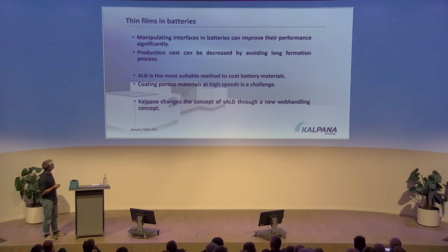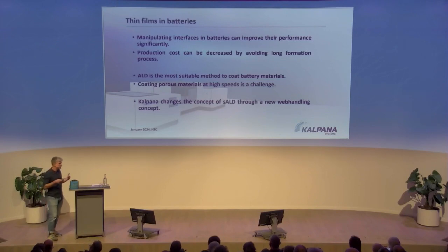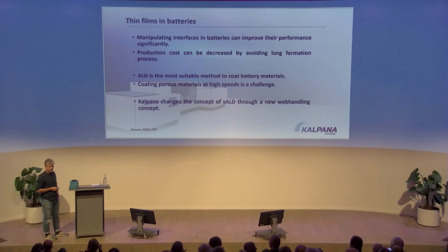This is actually a summary. So manipulating the interfaces of batteries can improve their performance significantly and even reduce the cost of batteries. ALD is the most suited method to do that. And we think for coating porous materials, you need something like we're doing, which is not basically an ALD invention. We didn't invent ALD, but we did invent a new way of web transport, which is very well combined with ALD to make it compatible with mass production of batteries. Thanks.